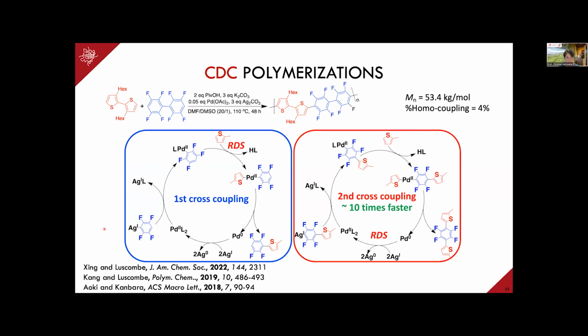But what we have been able to do is, inspired by work performed by the Kanbara group, also based in Japan, this reaction right here, this is a CDC polymerization. If you do this reaction, you get really great molecular weights with minimal homocoupling. What we were really able to identify is the mechanism of this polymerization that allows this reaction to go as well as it does. So now that we have this mechanistic understanding, we're trying to move towards making other types of polymers using this CDC polymerization.